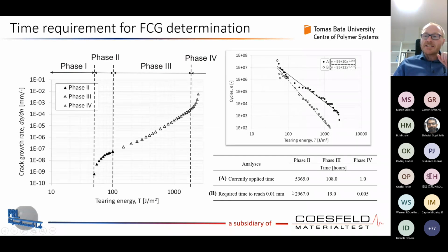And what you can see is that, only for the B measurement, we need for the evaluation of the phase 2 close to T0 approximately 3,000 hours of measurement. Whereas for the stable crack growth, the phase 3, we need only 19 hours. And for phase 4, close to the ultimate strength, the critical tearing energy, we need 0.005 hours to have it.